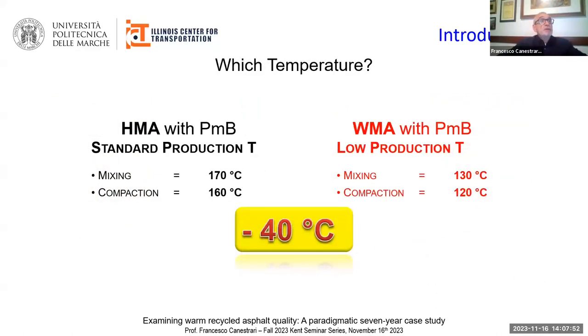Another starting point was the temperature reduction that was fixed equal to minus 40 degrees C to obtain the benefits in terms of pollution reduction at the asphalt plant and not only. As a consequence, the mixing and compaction temperature for warm mixtures containing polymer modified binders were assumed equal to 130 and 120 degrees C respectively.